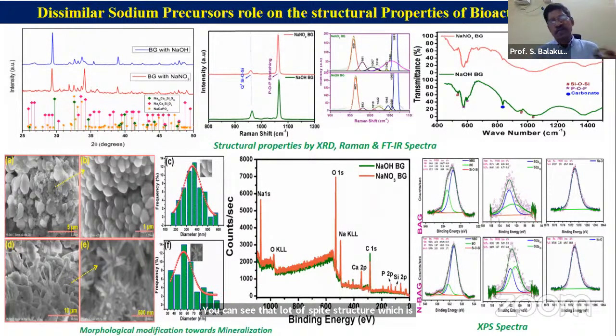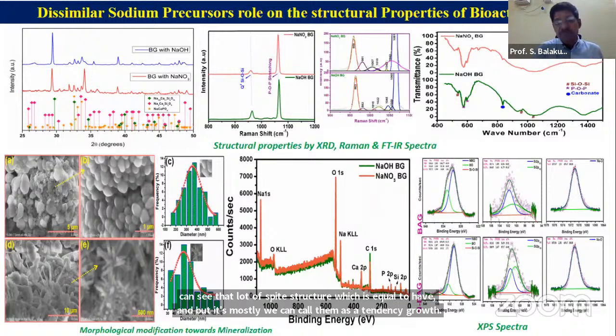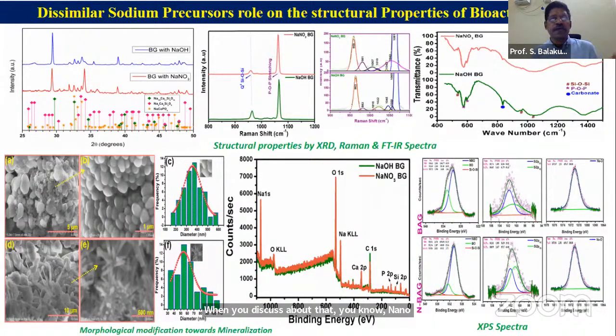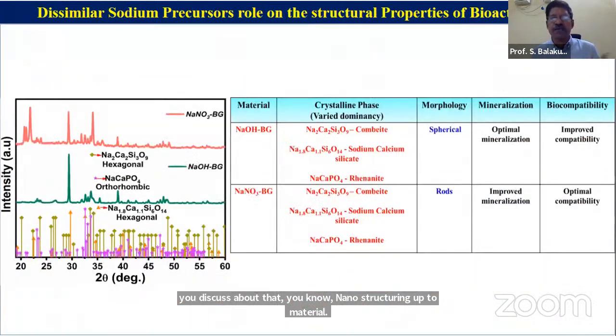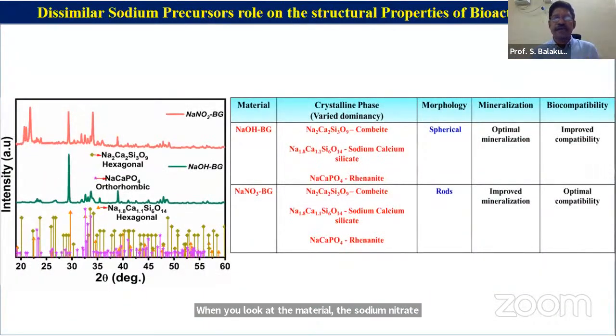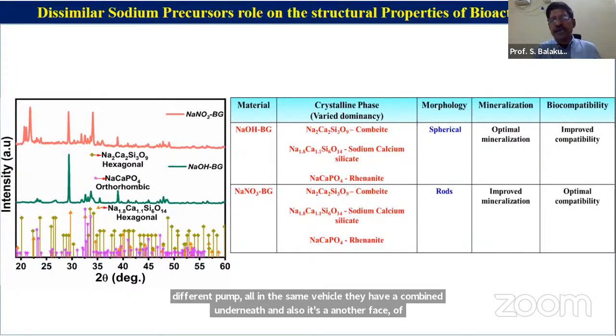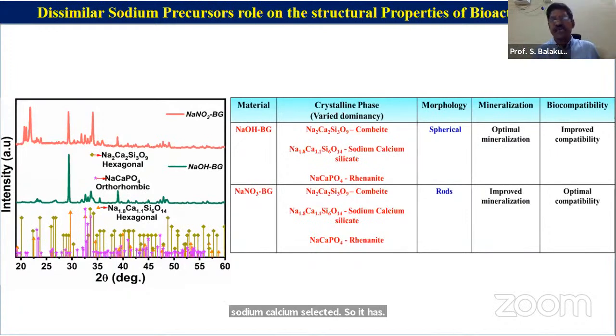We can call this a tendency growth when you discuss the nanostructuring of the material. The sodium nitrate based one is less toxic and biocompatible, but you can see that it has three different compounds in the same material: combeite, rhenanite, and another phase of sodium calcium silicate. So you can reduce the size, but the change in the pH also yields an additional phase. So there is a difficulty in controlling this kind of work.